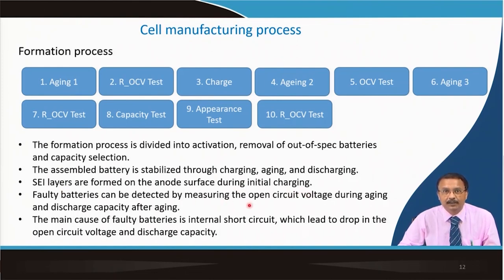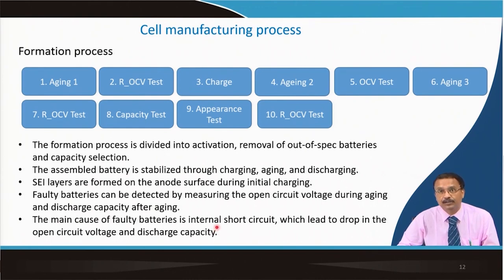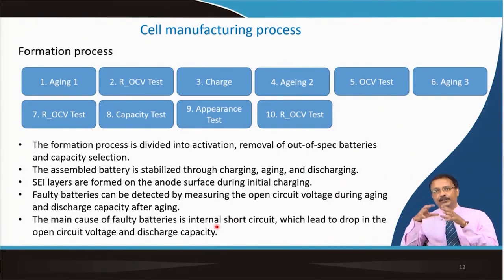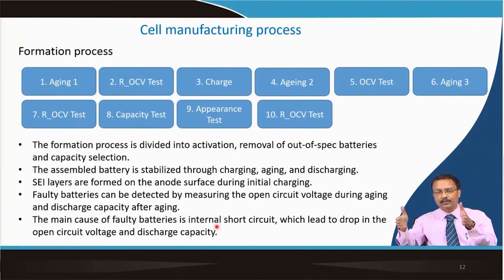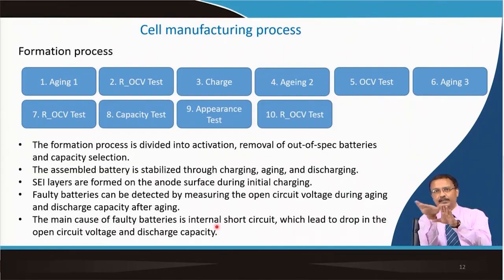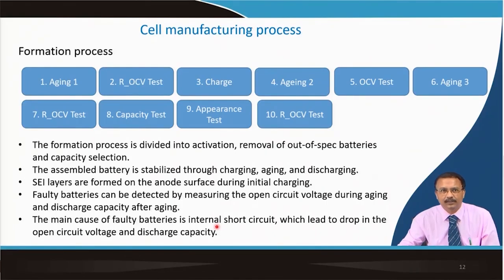Faulty batteries can be detected by measuring the open circuit voltage — it usually should be in the range of 2.5 to 3 V. If it is bad, the battery is discarded. The main cause of faulty batteries is internal short circuit: if the winding equipment malfunctions, the anode and cathode — copper and aluminum in close proximity — can short circuit. If the separator is misaligned and the cathode is touching the anode, there will be an internal short circuit. These are precautionary measures you must take.